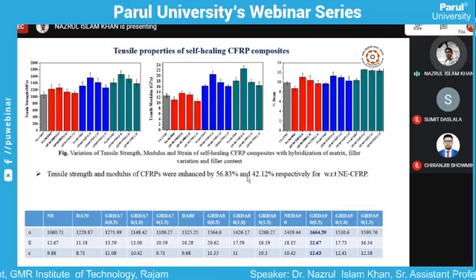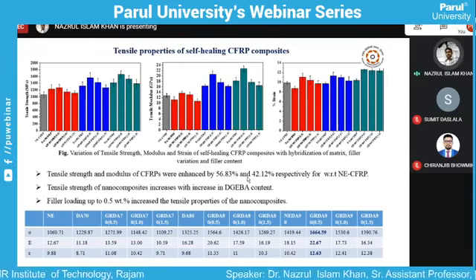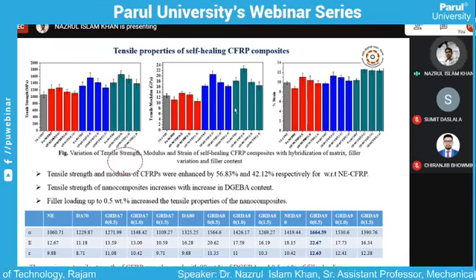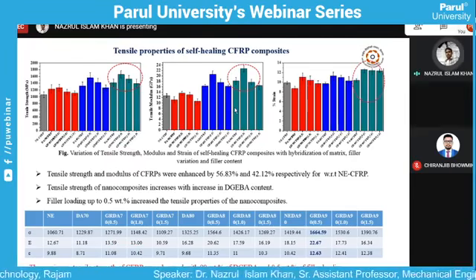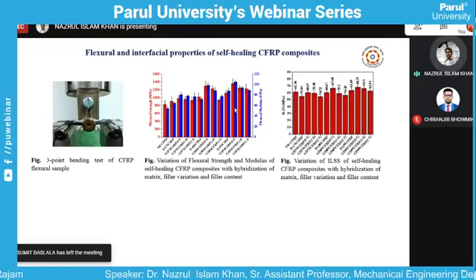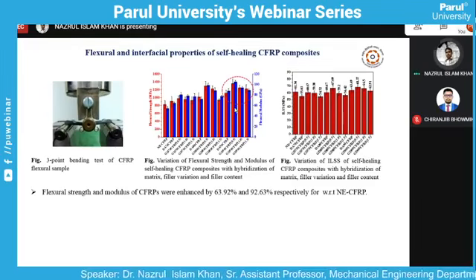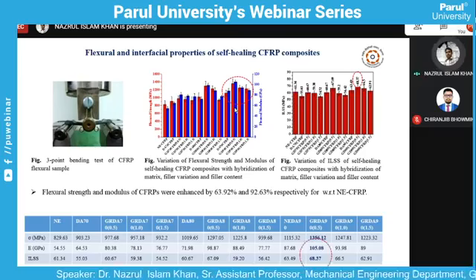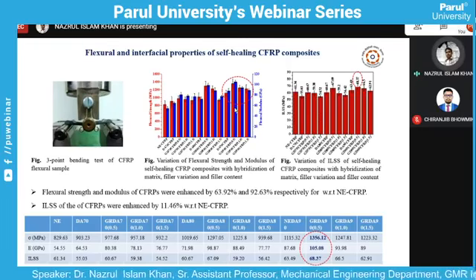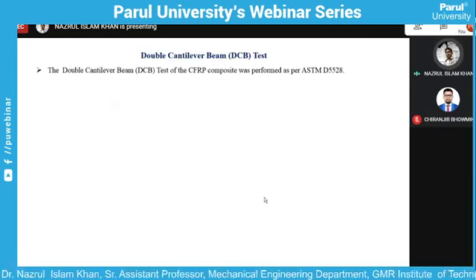We also prepared a carbon fiber. First we tested in nanocomposite, then we prepared the CFRP composite and found the same thing - in CFRP also we got this enhancement. Then we tested the out-of-plane mechanical properties and found a huge enhancement in the flexural properties, like 63% enhancement in out-of-plane mechanical properties.